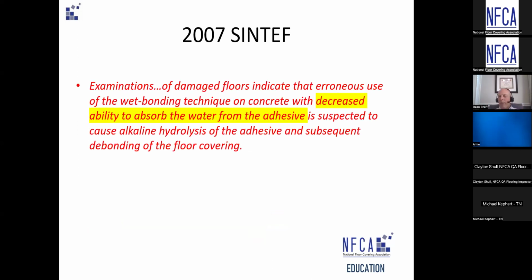So again, as I round up with 2007, they actually did plenty of examinations on failed floors, and they found out that quite a few of the damaged floors were not the result of concrete moisture. They are actually the result of the misapplication of adhesive on a non-absorbent substrate. That water had no place to go. The alkalis raised up, and then it started attacking itself.